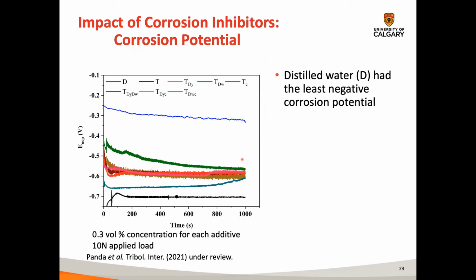So we first looked at, we compare D means distilled water, T means high TDS water, and then the subscripts here mean the additives that we tested. So we tested distilled water here in blue. It had the least amount of corrosion, or is the most resistant solution to corrosion. Then we tested the steel in the high TDS water, this T, which is down here at the back. It's the most corrosive solution.